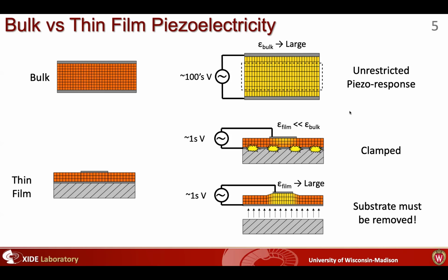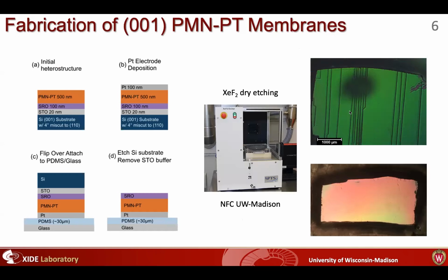But I draw the figure this way because when working with thin films, you have to pattern your top electrodes. You can't use the entire top surface because then you'll find a defect somewhere that'll short your capacitor structure. So you find yourself polarizing kind of smaller regions. And I draw the figure this way because there's actually some additional mechanical boundary conditions that result in these membranes.